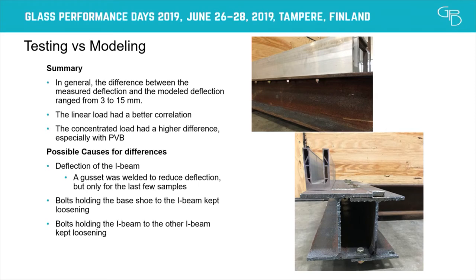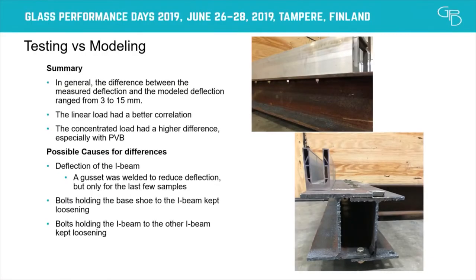The first time we tried impacting, the lab thought, oh, this huge I-beam here is strong enough, it's heavy enough. The impact actually lifted the whole unit over and moved it about 10 centimeters. It's a pretty major impact. So the lab then bolted it down to the cement. One other thing that we did was we welded a gusset onto the I-beam here to prevent the I-beam from rolling. Unfortunately, this was towards the end of our testing, and only a few samples actually got tested with that.